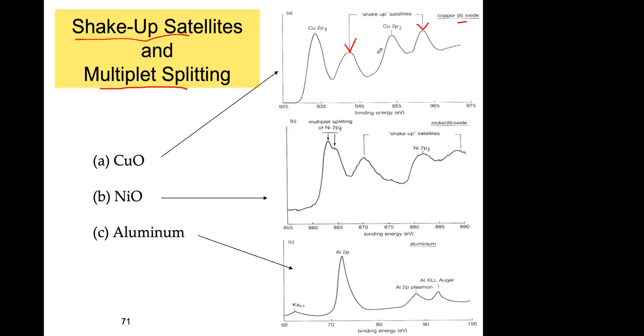And this is so impressive that for copper 1 or copper 0, you don't see those peaks. So again, these peaks are a fingerprint of copper 2. You can really easily determine that it's copper 2 by looking at a copper 2p binding energy region for a copper sample. In this case, it's copper oxide.